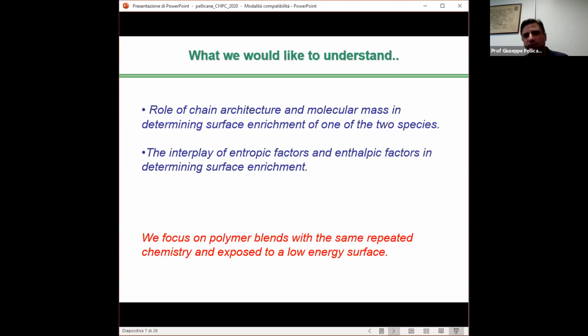While a number of previous studies focused on how polymer diffusion is affected by polymer topology, the role of chain architecture and molecular mass in determining the polymer species that is going to get preferentially adsorbed at the interface is not yet well understood. So by focusing on this aspect, we try to understand the interplay of entropy factors, such as the architecture and molecular weight of the polymers, and enthalpy factors, due to the different cohesive energy of the two polymer species, in determining which species is more enriched at the surface.